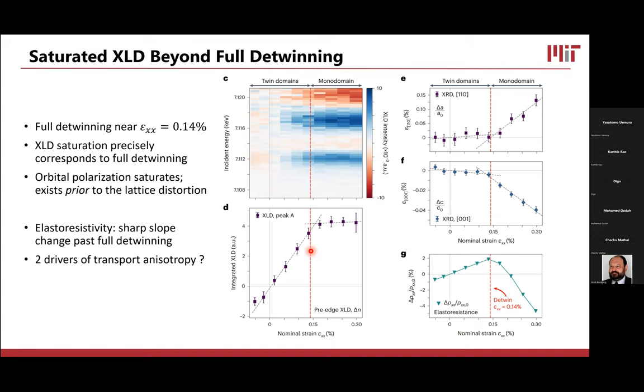This actually comes back to the question that I was going to ask you. Your central claim is that when samples are fully detwinned, your orbital occupancy is completely saturated, and you suggested that the spin occupancy is not completely saturated and will continue to increase with strain. That assumption, I don't think is actually correct. I don't think there's any measurement suggesting that when you fully detwin the sample, if you further strain it in the ordered state, you can change the spin anisotropy further. I don't think there's evidence for that.